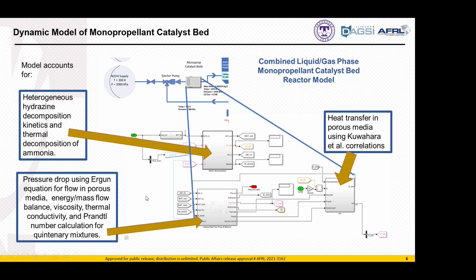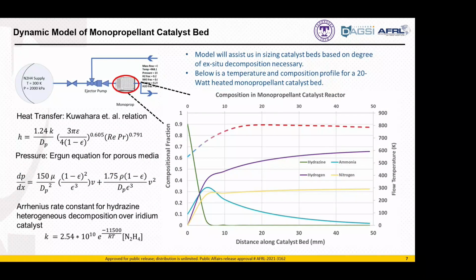But we account for all the flow dynamics, and this even has in here temperature and pressure variable thermophysical properties and calculates effective properties of chemical mixtures as well, and also looks at the heat transfer phenomena. So just real quickly here, this is just an example of the hydrazine decomposition. We want to decompose as much of that hydrazine as possible and flow just purely hydrogen, ammonia, and nitrogen into the anode of the fuel cell. So this is just an example of the decomposition that is happening here. And we do decompose pretty much all of our hydrazine here with this design.